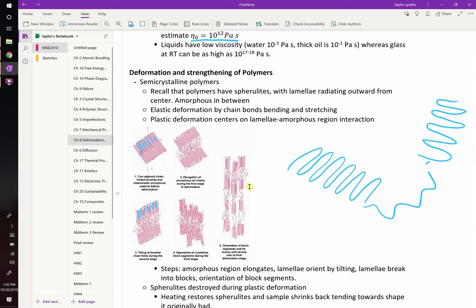Right, you anneal it, just like you do with metals. We've stretched this polymer. It's massively deformed, right? We were able to get huge strains out of it because this happened. I heat it back up, what's going to happen? It's going to tend to go back to this because this has more crystalline regions, which give you an enthalpy bonus because they're bonded together better, right?